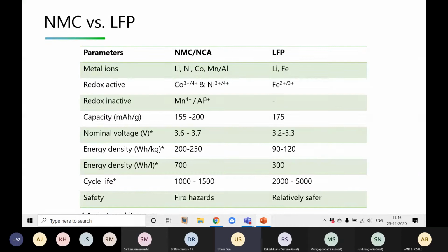And the LFP is slightly different, the class of the material is slightly different. In case of NMC, this cobalt and nickel is the active redox couple. So it's changing this redox from cobalt. In case of cobalt, it is changing from +3 to +4 state, and in case of nickel, it is changing from +3 to +4 state.